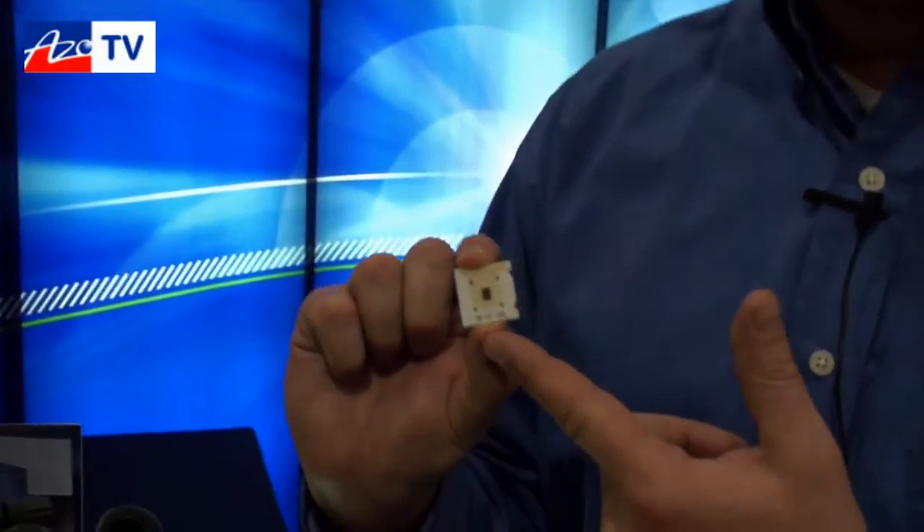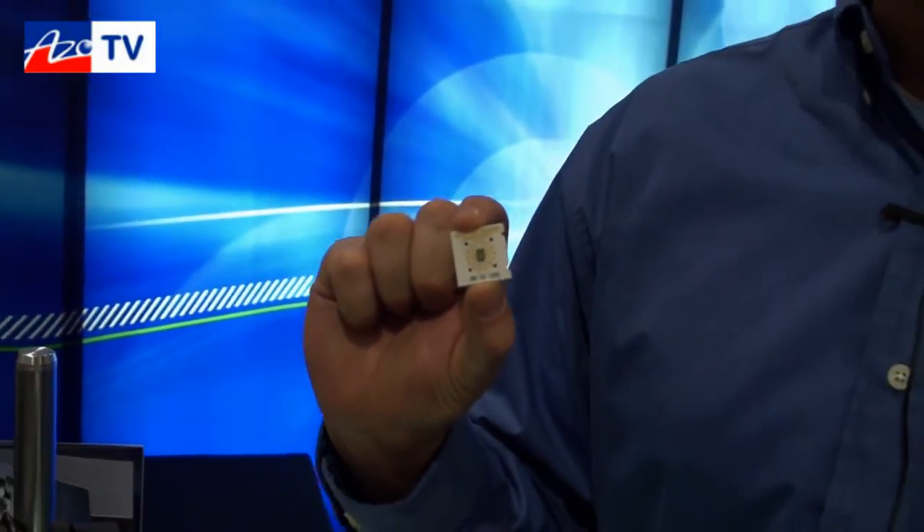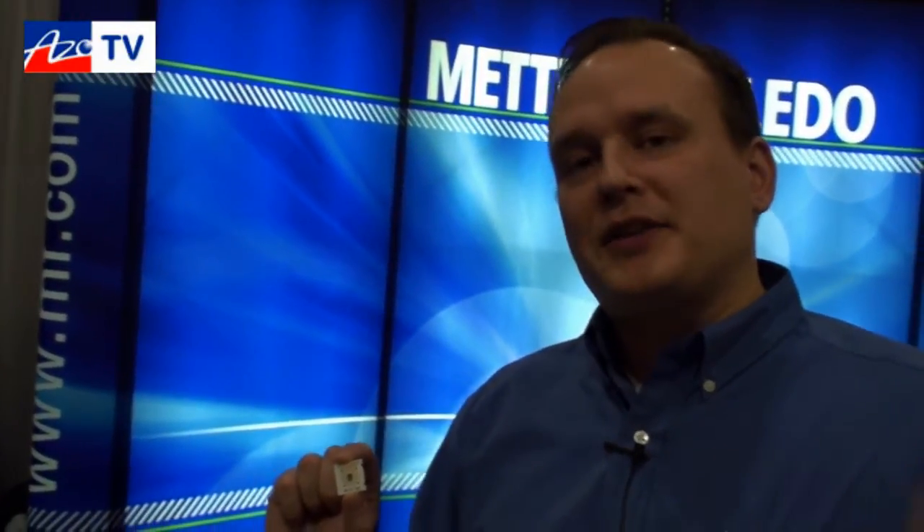Those small sample chips — they're easy to keep and archive samples with? Absolutely. Each chip is serialized and they're meant to be archived. What's really novel is that as long as you go through the melt and don't physically decompose the sample, you can actually rerun them. You can measure things like what's the critical cooling rate to make my polymer system completely amorphous, or what is the critical cooling rate for crystallization to occur. These parameters are very important when thinking about the molding and manufacturing of high quality parts.